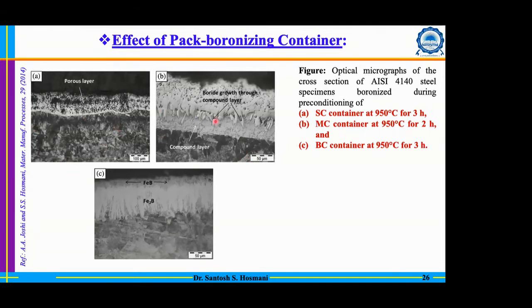That is a small container, medium-sized container, and large container. I mentioned that the container material is a steel. It can be stainless steel or even a mild steel. You have to remember that during boronizing, your container will also consume the boron potential which is generated. And most of the time, you have to take care of that. That's why people used to pre-treat the container itself first, so that the consumption of the boron potential by the container will be minimum. However, some consumption will always be there.